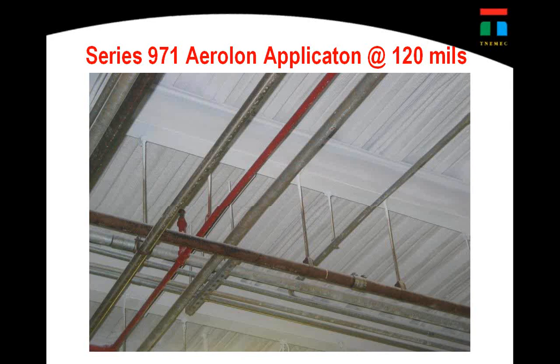Now think of this technology as kind of like moisture vapor drive under a slab. Under vapor mitigation issues, you have moisture penetrating up through a concrete slab. It basically reaches a certain pressure that blows off the finished material. What they do is put down moisture vapor mitigation technologies that basically don't stop, but slow the migration of moisture so slowly through the films that it doesn't blow off a finished flooring product. Well, the same thinking takes place with aerogel materials.